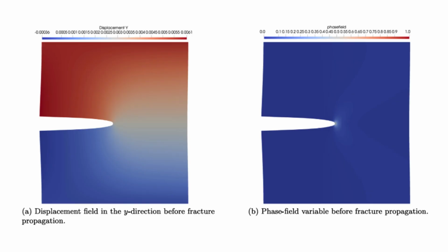Okay, solve for stretch and squash. Right. Then you freeze those calculated displacements, and you solve for how the damage field should evolve or change based on those stresses. And you just bounce back and forth. You repeat that cycle: solve displacement, solve phase field, solve displacement, solve phase field, until the changes become tiny, until it converges to a stable solution. That makes sense for stability. It avoids tackling the whole coupled mess at once.